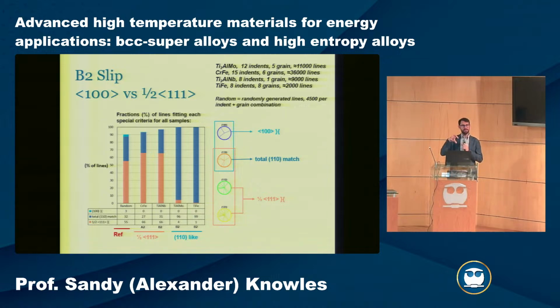And so we now have this indentation method that takes on the order of an hour or two to characterize the slip behavior of a new material. So we can now iterate composition. We can melt new alloys. We can also make composition graded materials, and we can evaluate the slip behavior.